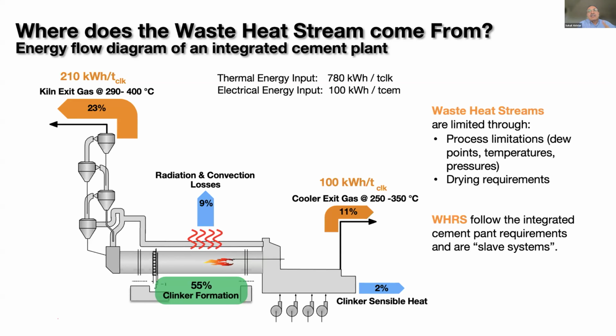The other is wasted in the form of hot gases coming out of the preheater. And if you see on the left-hand side, there is a tower, the preheater, the cyclones. The raw material, as it goes in, is preheated in the preheater before it goes into the kiln. The hot gases that are leaving the system, they leave somewhere anywhere between 300 to 400 or even higher than 400 degrees. And then the clinker comes out of the kiln on the right-hand side, and it goes at very high temperature